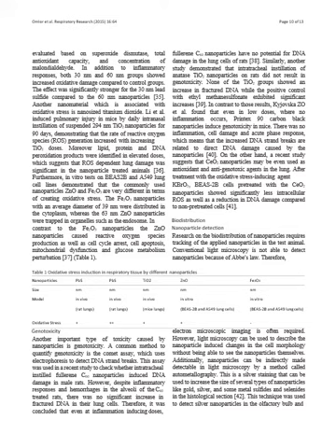male rats. However, despite inflammatory responses and hemorrhages in the alveoli of the C60 treated rats, there was no significant increase in fractured DNA in their lung cells. Therefore, it was concluded that even at inflammation-inducing doses, fullerene C60 nanoparticles have no potential for DNA damage in the